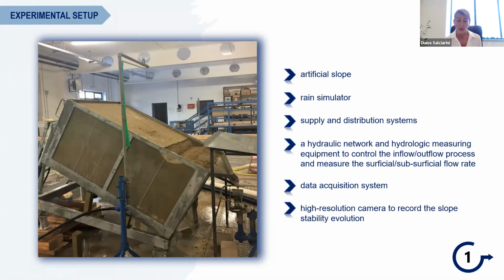The small-scale slope, as you can see, is made of a galvanized steel box with a plexiglass side wall for the complete observation of the mechanical phenomena that occur. And the box can have different inclinations controlled by hydraulic pistons at the base. Here, the small-scale slope is represented in its final configuration used for the analysis, with a maximum inclination of 30 degrees and a local modification of the geometry in the lower part of the topographical surface to simulate the presence of an excavation work.